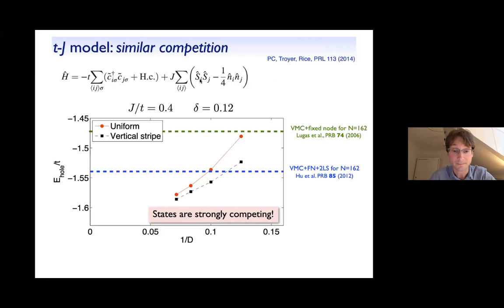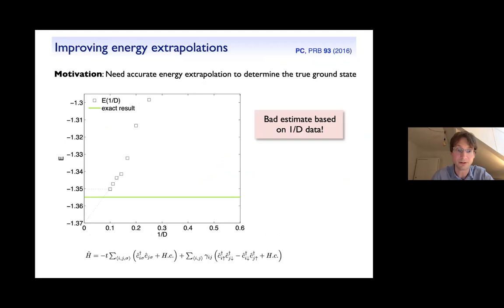So in the end, what you see here is very similar to the Hubbard case, namely you have two competing states, uniform and stripe states, which are very close at large bond dimensions. And then the question is really, how can we extrapolate these energies to the exact infinite D limit as accurately as possible to really find out which of those competing states is the true ground state. Now, the problem is often, if you do this as a function of the bond dimension, that results are not necessarily very accurate. So let me show you one example to illustrate this.